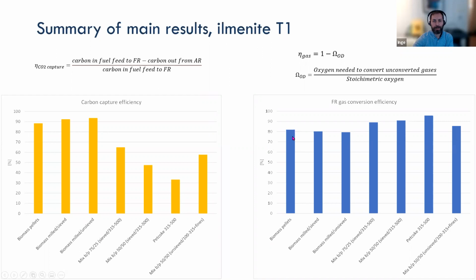Yeah, and the fuel reactor gas conversion efficiency is convenient because it's only dependent on the gas composition. We can calculate it from the gas composition out of the fuel reactor. It's defined through this oxygen demand, which is the ratio between the oxygen needed to convert the unconverted gases to the stoichiometric oxygen. And the gas conversion efficiency is then 100% minus the oxygen demand in percent.